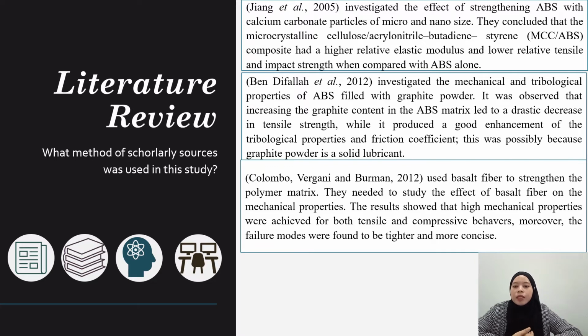Colombo, Vergani, and Burman in 2012 used basalt fiber to strengthen the polymer matrix. They studied the effect of basalt fiber on the mechanical properties. The results show that high mechanical properties were achieved for both tensile and compressive behavior.